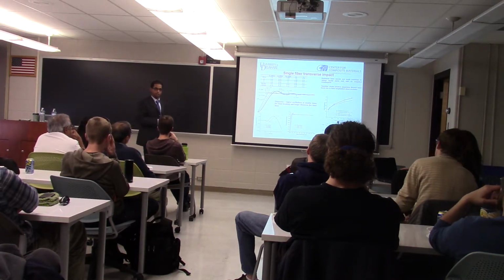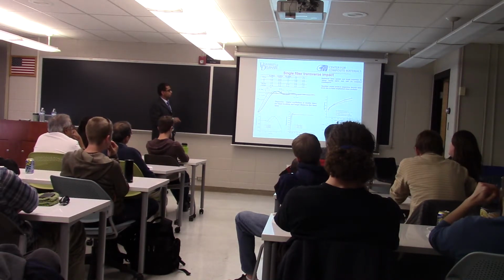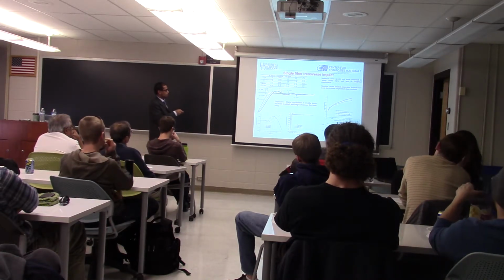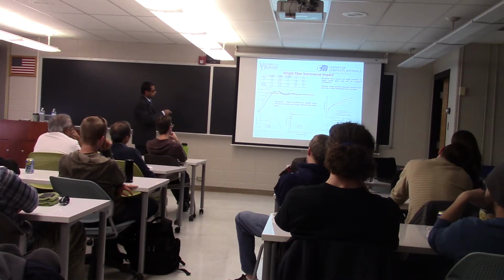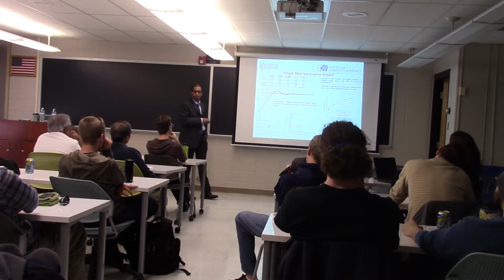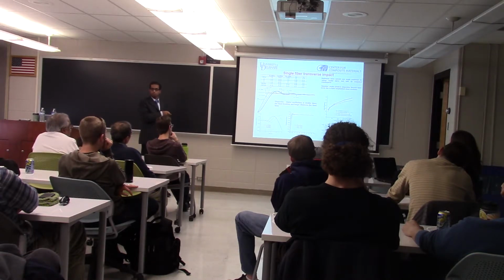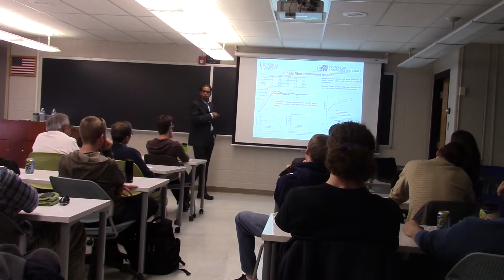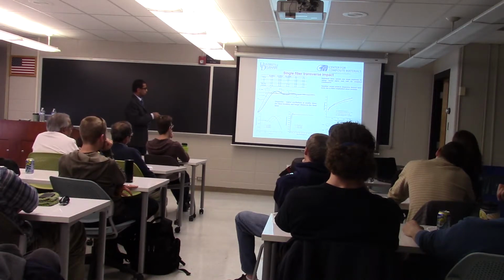Now, most of the literature is focused on axial tensile loading, whereas the consideration of bending and its effects is very limited. So we wanted to understand the role of the longitudinal shear modulus. We did a parametric study on this longitudinal shear modulus G13. When G13 is negligible, the transverse wave is a straight line because the fiber is highly shear deformable with no flexural resistance. As G13 increases, bending begins to dominate, and the model predicts a dispersive flexural wave in the fiber. So the high frequency component of the wave travels faster than the low frequency component. So for a fixed location, you have higher oscillations for smaller times, and for a fixed distance, you have higher oscillations at longer distances.